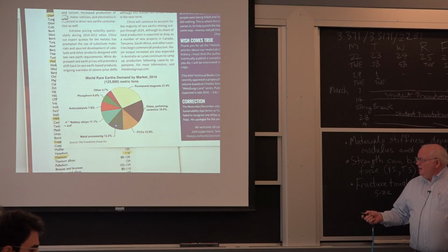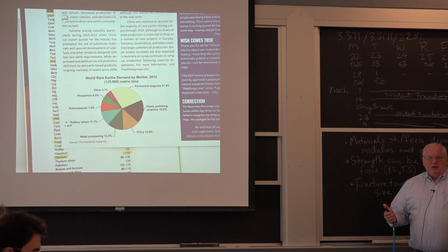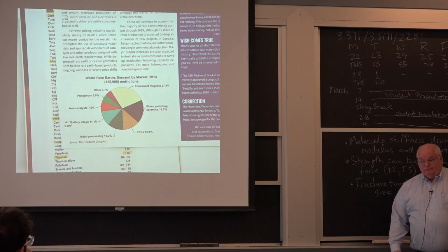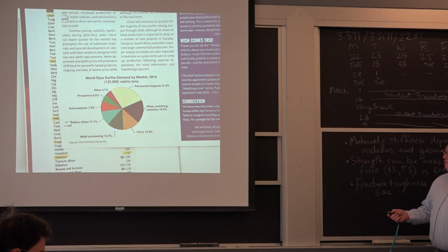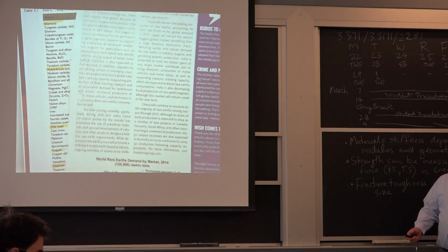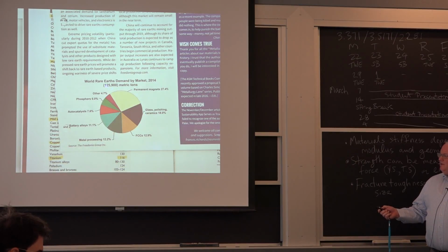Metal processing. Turns out 12%. People use cerium in steel to tie up the sulfur. And there's 1 billion tons of steel, so it doesn't take very much cerium in steel to end up being a fairly large fraction of the total. Catalysts, phosphors, a number of uses. Battery alloys. I don't even know what FCCs are. But in any case, to give you an idea, okay, 125,000 metric tons compared to steel, which is 1 billion metric tons. We're talking orders and orders of magnitude larger.